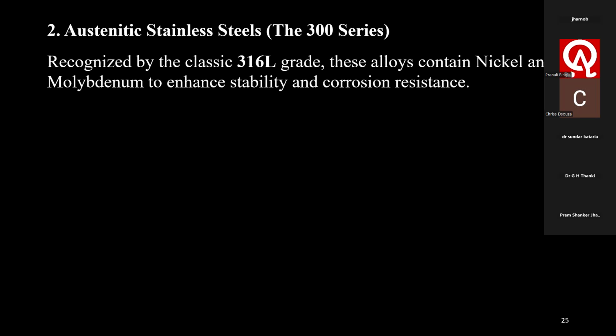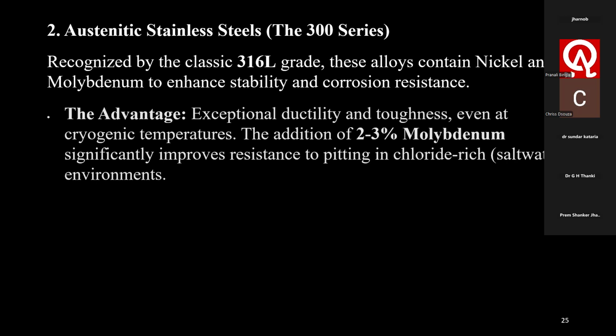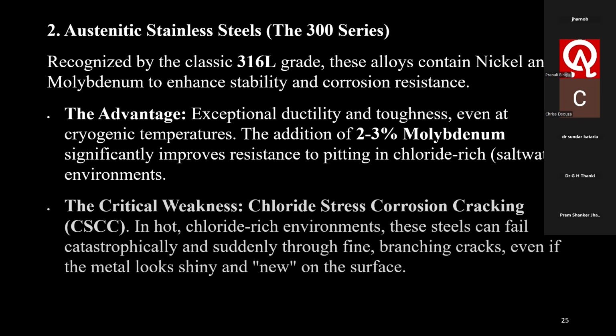Next is the austenitic stainless steel, which is very fondly known as the 300 series, recognized by the classic 316L grade. These alloys contain nickel and molybdenum to enhance stability and corrosion resistance. What is the advantage? Exceptional ductility and toughness, even at cryogenic temperatures. The addition of 2 to 3% of molybdenum significantly improves resistance to pitting in chloride-rich, that means saltwater, environments.